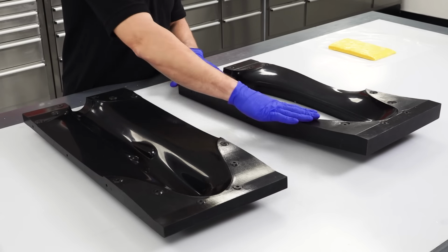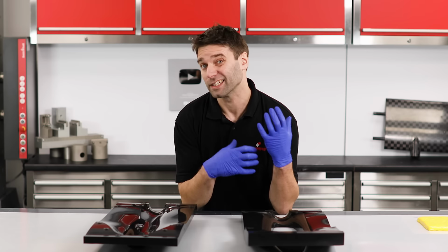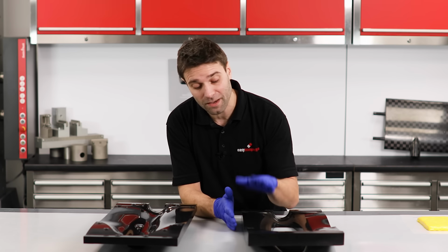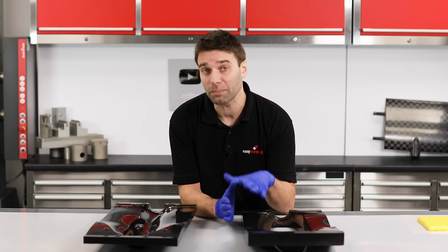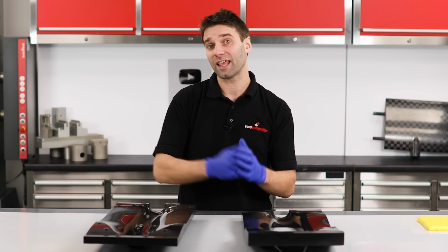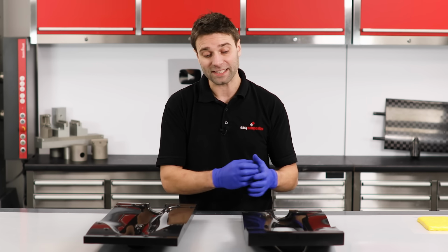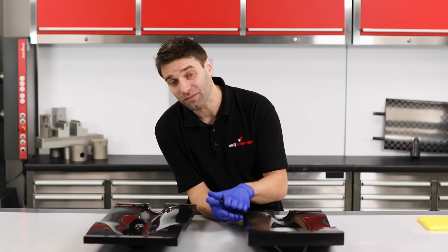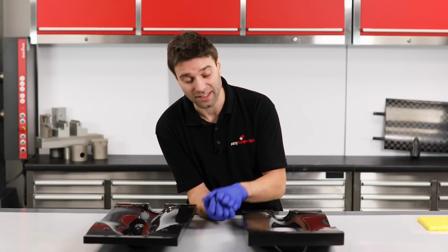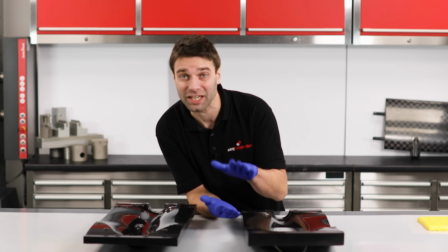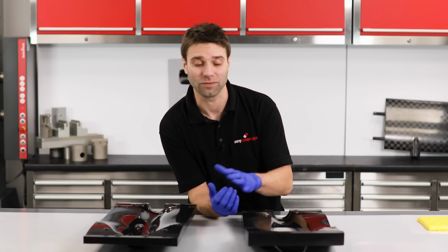But for this wing root area, I'm actually going to be taking a slightly less common strategy and make my inserts directly against the mould surface. Now this is only possible if you've got a very thin laminate of 1 millimeter or less, as it doesn't account for any of the material offset that you get. Instead, it relies on sort of squashing and compressing that silicone out of the way.